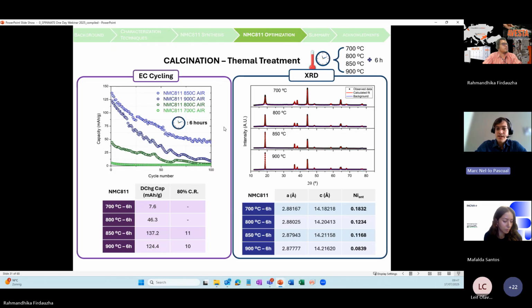And we'll start with XRD. In this case, I'm showing the spectra of these samples, and we can see that the 700 degree and 800 degree samples show a really poor crystallinity with broad peaks, with not well-defined split peaks, while when you increase the temperature, you obtain much better defined peaks with better splitting. And if you also look at the lattice parameters that I was mentioning at the start, you also see that these 700 and 800 are not in the right range. Looking at the nickel antisite effect, this lithium-nickel cation mixing, you see that by increasing the temperature, you also get a lower nickel cation mixing. However, it is still at a very high value.